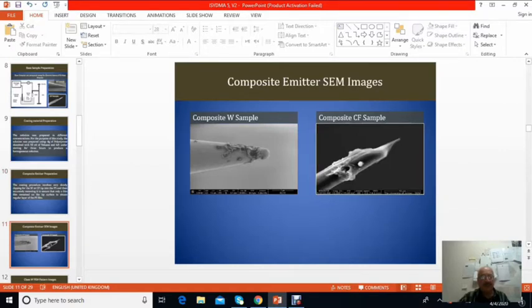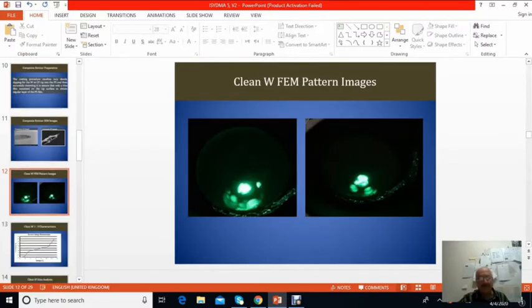Composite emitter SEM images. This is the composite emitter of the tungsten tip. You can see the coating, and the composite carbon fiber you cannot see through because the carbon fiber is not real metallic, so you cannot see through. But this was the carbon fiber tip, and the coating was there.